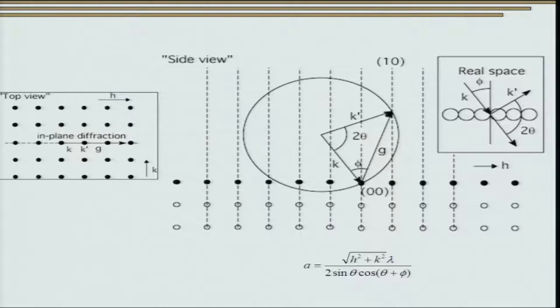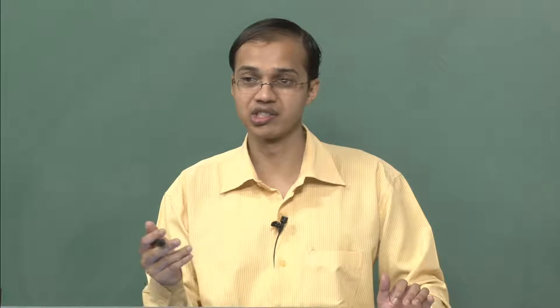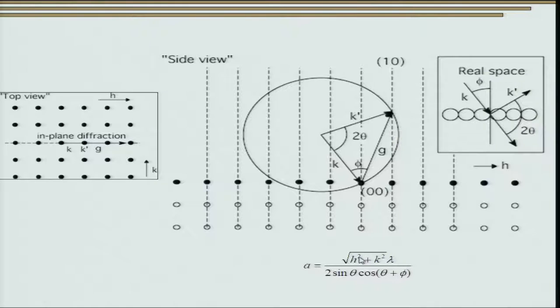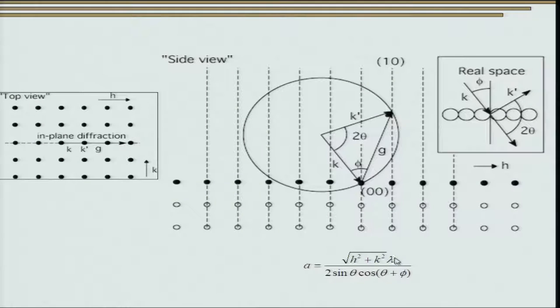In this figure, we have shown the projection of the Ewald sphere. Instead of having a complete space group, we have a plane group, and therefore instead of getting a structure factor in terms of hkl, we are just restricted to h and k. Depending on the geometry, you can derive the Bragg's law for the 2D plane condition. The term 2 sin theta cos(theta plus phi) accounts for the incident angle, and the square root of h squared plus k squared is analogous to the interplanar distance in Bragg's law.